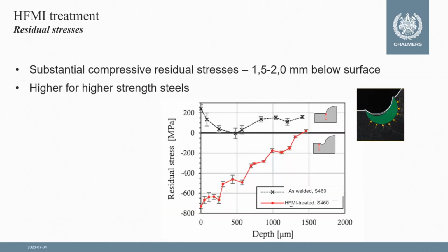The compressive residual stresses will depend on several parameters: the intensity of treatment that you can set in the tool, the type or strength of the steel that is treated, and so on. But it's typically between 1 and 2 millimeters deep below the surface, and it can go up to very high compressive stresses. They account for the major part of the enhancement that this technique provides. It's very important that we have these compressive residual stresses in this kind of treatment, which we of course don't have with either burr grinding or TIG dressing in principle.